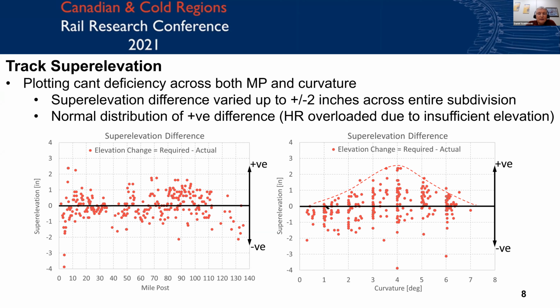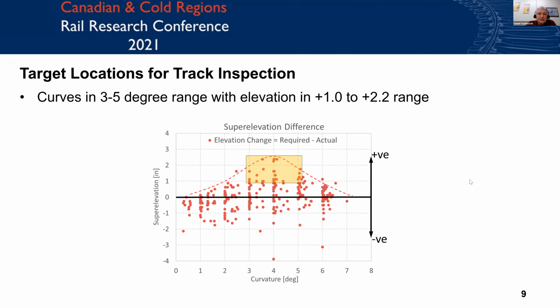In fact, if you look at the cant deficiency, so the high rail damage, it has more of a normal distribution with a lot of the positive numbers for the cant deficiency being between 3 and 5 degree ranges. So we thought this was interesting because the derailment that we looked at happened in a 5 degree curve, so around that point right there. So we decided to focus on that, and for our inspection, focus on 3 to 5 degree curves that had the super elevation in the +1 to +2.2 range. And we selected about 30 different curves and inspected them over a 2-day visit, and some of the results from that visit are in the paper, and I'll just show you the highlights of that now.